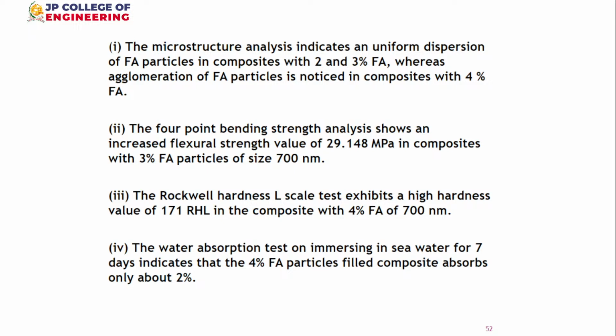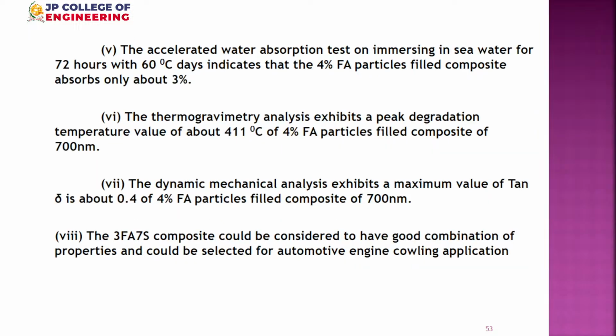Next slide, please. The accelerated test also proved that 4% absorbs more moisture. And thermogravimetry showed that we can increase the thermal stability by the order of even 40% and so on. Dynamic damping behavior also we observed, a high damping in this one. So finally the 3% fly ash with 700 nanometer composite can be considered as a good combination of properties and could be selected for automotive engine cowling application.